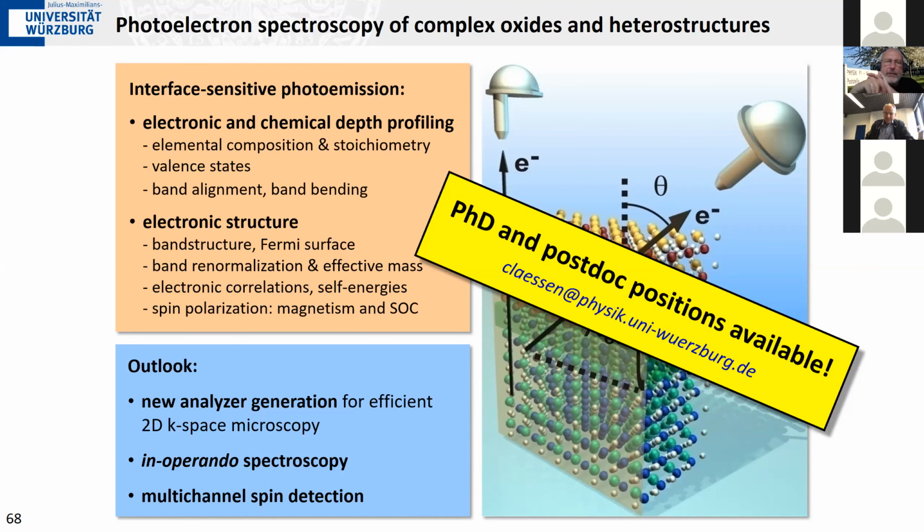You have to be careful though, because we found that the reference spectra that are often quoted in the literature for the trivalent spectrum very often include a very strong titanium 4+ contamination in them, because people haven't often realized that you always have a very strong 4+ contribution. Yeah. Okay. That's one thing that works in this case quite well.